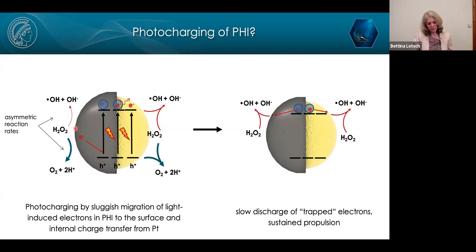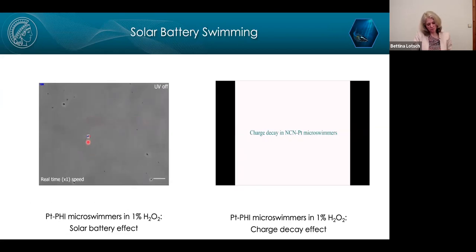But if we have this asymmetric surface reaction, then we can imagine that if hydrogen peroxide oxidation at platinum is very efficient, the electrons from the platinum can be used to quench the holes on PHI. That can then lead to an accumulation of electrons on PHI. So this is at least a theoretical possibility. And in fact, what we observe is pretty much exactly that. Here you see a swimmer in the dark. The light is turned off, and now we turn on the light, and the swimmer moves. And now we turn off the light, and the swimmer continues to swim.